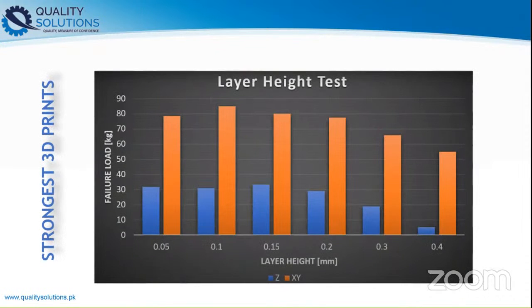Therefore, the ratio calculation between the nozzle diameter and layer thickness enables us to generalize the results. Applying this to our test results means that starting at a layer thickness of more than half of the nozzle diameter, we can expect that the strength of the parts will suffer. This means that for a strong 3D print with a 0.4 mm nozzle, which normally comes with 3D printers, probably don't go above 0.2 mm layers.